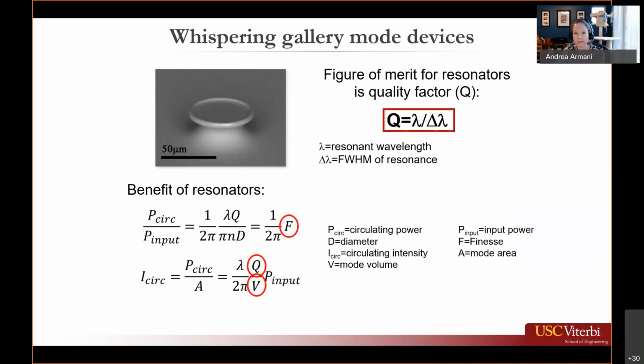and you measure the linewidth of the cavity. The reason why Q is an important metric is because it's used in the calculation of both the circulating optical intensity and the circulating optical power. And both of those determine the intensity or that amplification of power that your resonator can give you. Obviously, there are many other metrics of interest, like the optical mode volume and the finesse of the cavity, but Q underpins all of those other metrics. So it's usually the first metric that you measure after the resonance wavelength.